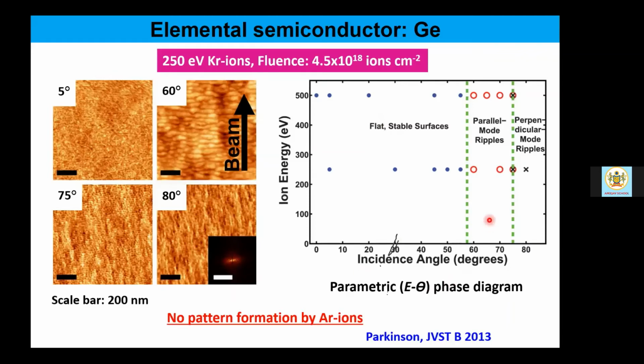It's very clear that up to an incident angle of nearly 58 degrees, there is no pattern formation. It remains a flat, stable surface. And then over an angular window of nearly 57 to 75 degrees or so, we get to see parallel mode ripples. What are parallel mode ripples? Where the ripples are running perpendicular to the ion beam direction. The example is shown here, corresponding to an incident angle of 60 degrees. Very interesting. Although for silicon we had seen a lot of pattern formation, for germanium similar ion energy and ion species doesn't give rise to any pattern formation.